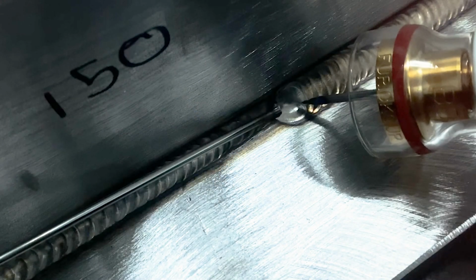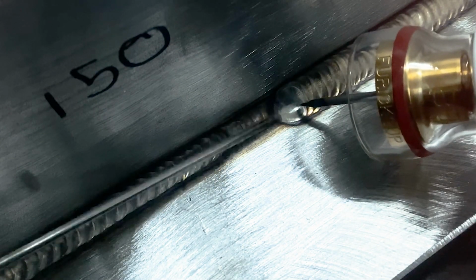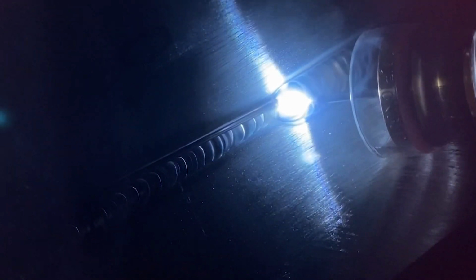And that tells me, again, that I should probably turn it up a little bit because I'm not getting the most out of my filler and my torch. Now stepping it up to 150 on the second pass using the lay wire technique. I truly feel like this is the sweet spot for this thickness of material. You'll notice the puddle's chasing me, but it's not uncontrollable. My travel speed is able to move up.